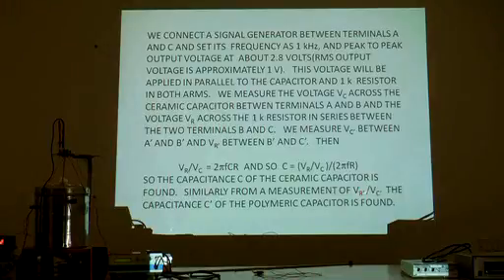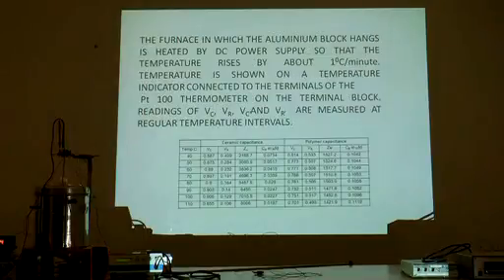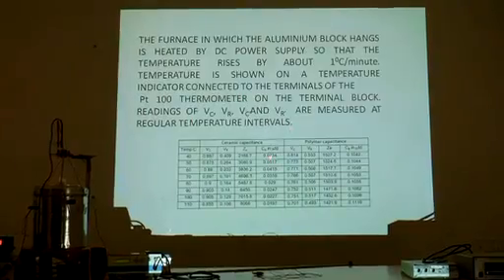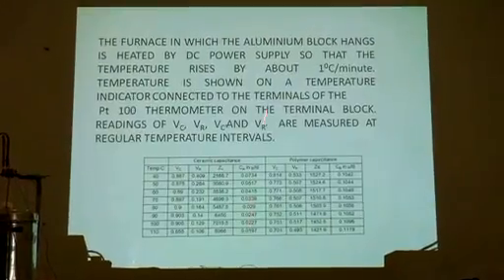I can do this for the polymer capacitor from the ratio VR dash by Vc dash measured on the left arm of my terminal block. So, I have the data here, 40, 50, 60, 70, and so on. For the ceramic capacitance, Vc is given in column 2, VR is given in column 3. The impedance, Vc by VR into 1K, is the impedance Zc. Zc is 1 by 2 pi fC. So, I get the capacitance C in microfarad.